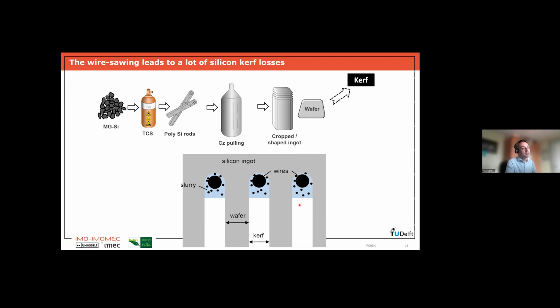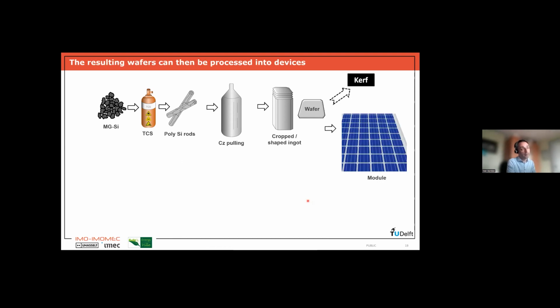silicon ingot. So after the cutting, you have the wafer, which has a certain thickness, which is determined by the distance between two wires. So typically the wafers used in industry are around 180 micrometers in thickness. But where the wire was cutting, you typically lose around 100 micrometer of silicon in the form of kerf losses. So after all these steps, we finally have wafers that are high quality and which can be used to make solar cells and in the end to make modules.